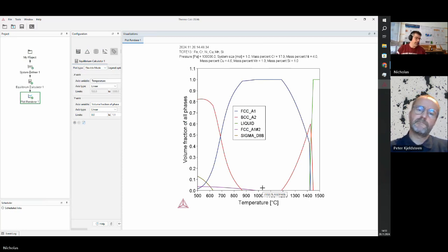So okay, this is then moving into a nucleation and growth calculation, right? Because what I do then is I try and set up a nucleation and growth calculation. But before I do that, I have to know out of which phase the copper precipitates, right? So I have to know what the matrix is. And just bear with me, because this is what I personally would do. The first thing I'd do is verify that this steel really has a martensitic transformation, that it really is a martensitic steel. That's the first thing I do.